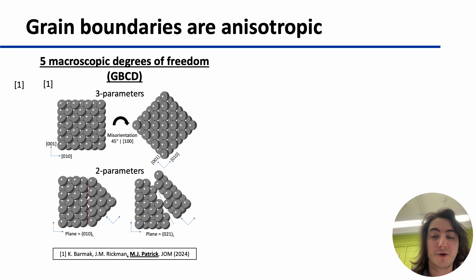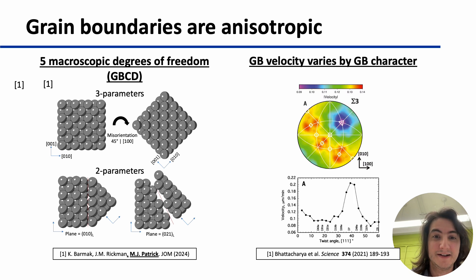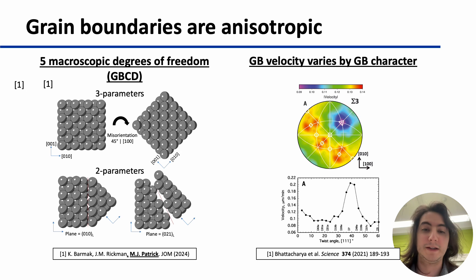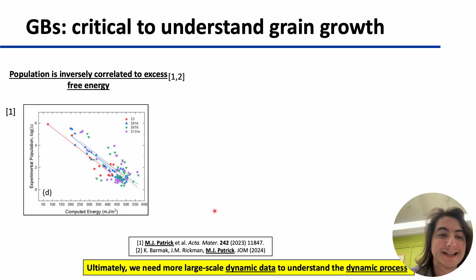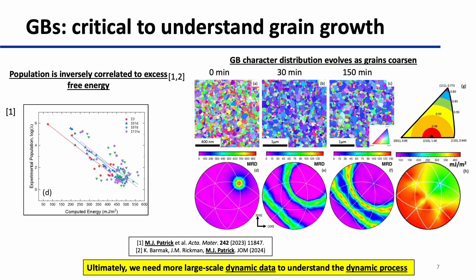It's important to consider all five of these parameters. Grain boundaries are observed to have velocities that tightly correlate to this five-parameter grain boundary character distribution. The properties of grain boundaries are critical in understanding microstructure and microstructural evolution. For example, we consistently observe that higher energy grain boundaries are observed with lower frequency than their lower energy counterparts.